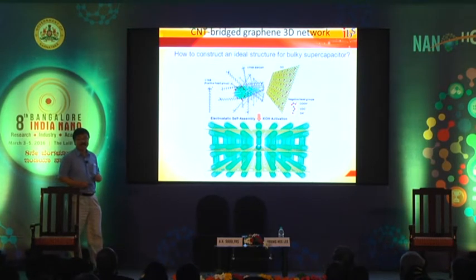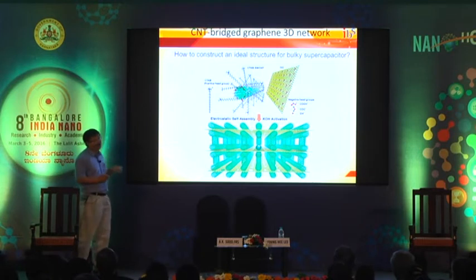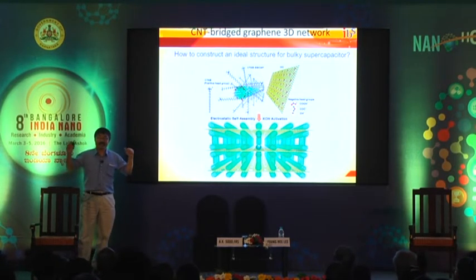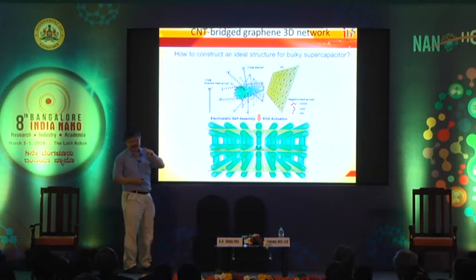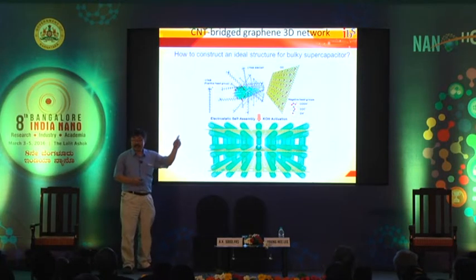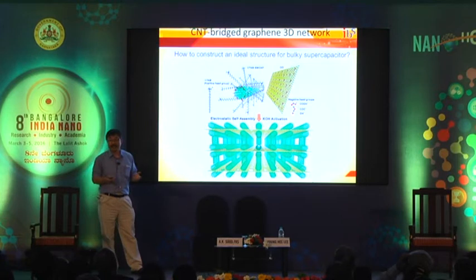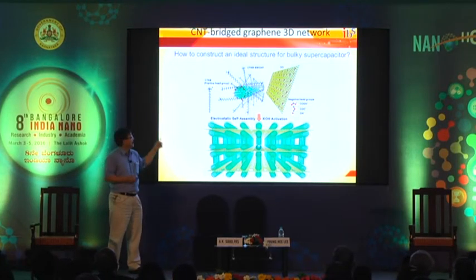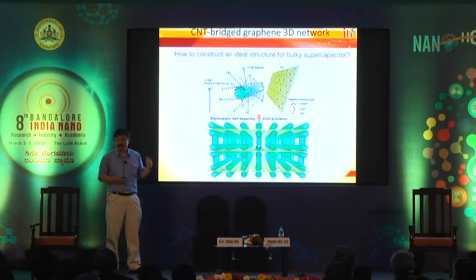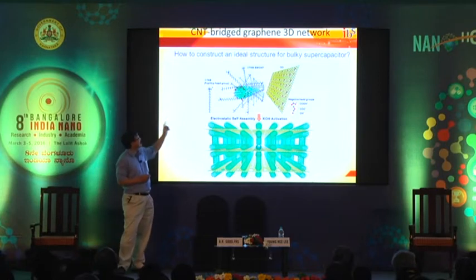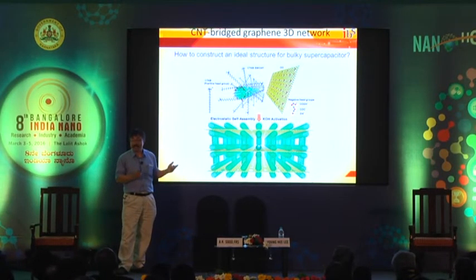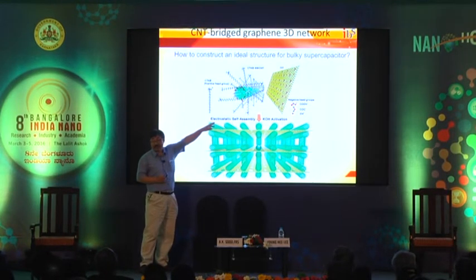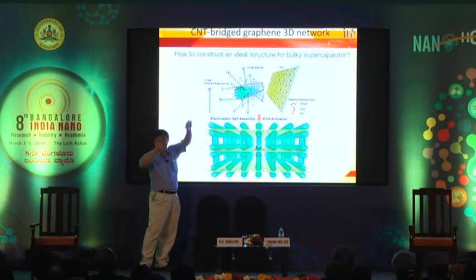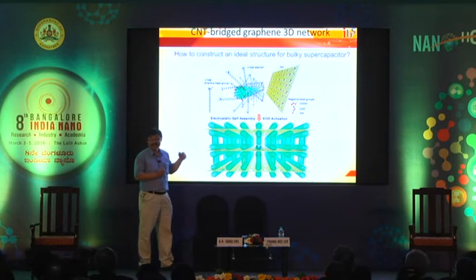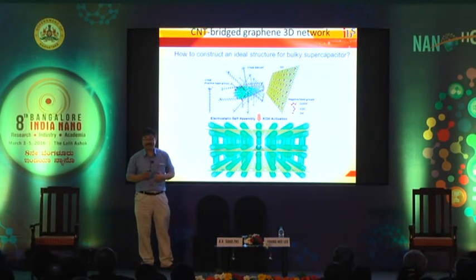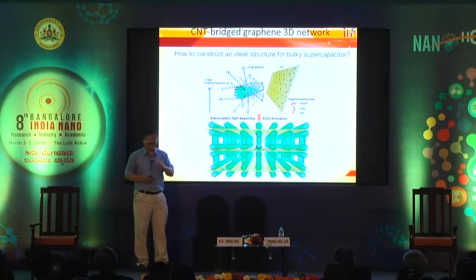So our idea, of course, is to take advantage of both materials. We can simply mix nanotubes and graphene oxide powder together. But there's a trick. Graphene oxide, GO, can be dissolved well in water because it's negatively charged. And the nanotube itself is hydrophobic and cannot be dissolved in water. So you need some kind of surfactant. In this case, the trick is to use CTAB, which has positively charged head groups. The tail part interacts with the nanotubes, and the positive head group is located outside. So when we mix them together in water, they form this electrostatic interaction and a microemulsion forms. Amazingly, we have this kind of structure.